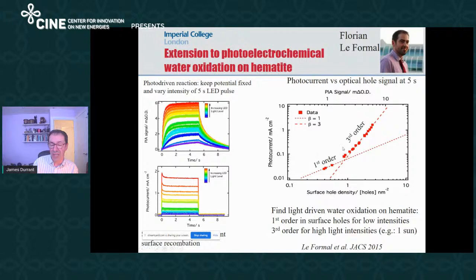And what we observe in this case is that at low hole densities, the flux of water oxidation is 1st order in hole density, which means essentially that the reaction of holes of water at low densities of holes, each hole reacts individually with water, most obviously to make hydroxyl radicals. But at high hole densities, the reaction goes up as the 3rd order in hole density, which as a number is rather surprising to us. We hadn't expected to see a 3rd order reaction. And so this is saying that every time you double the density of holes on the surface, the flux of water oxidation goes up as 2 to the power cubed, or 8 times faster.